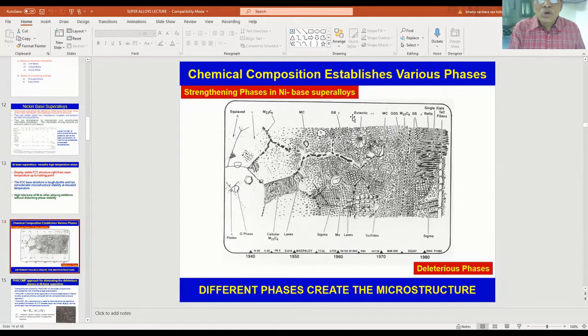Earlier, the composition was not controlled properly. I said that the physical metallurgy of the superalloys was not known before the 1960s. The alloying elements were just added, and there was no control of the size and shape of the phases that are getting formed. For example, when the superalloys were initially developed, the carbides, which are required in an isolated shape, were not there. Isolated particles of chromium carbides were not there. There was a continuous film, and some sort of silvery type of chromium carbide has been precipitated. This type of phase shape is not desirable for processing.